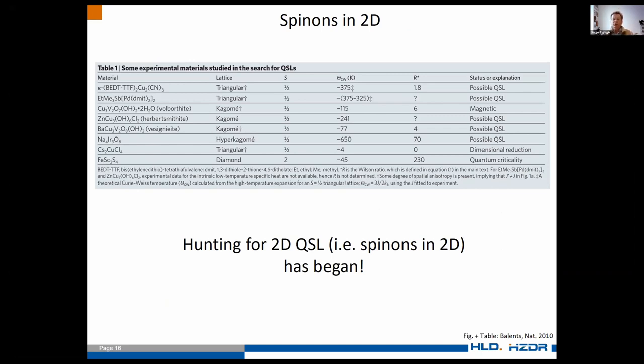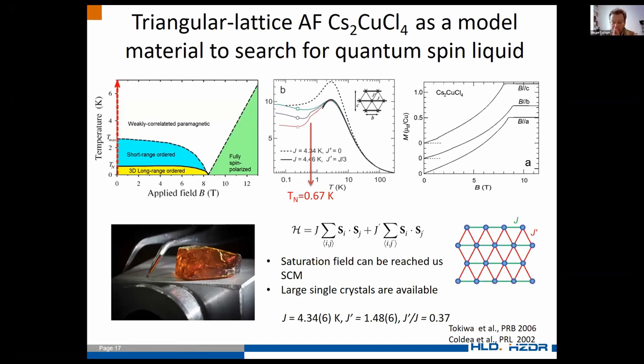If we talk about two-dimensional materials, there is not such a big number of two-dimensional materials where this quantum spin liquid can be expected. So we end up with Cs2CuCl4. This material has a two-dimensional triangular lattice structure. It is ordered antiferromagnetically at about 0.7 K. But above this temperature it is magnetically disordered, and this is where we might expect the quantum spin liquid.